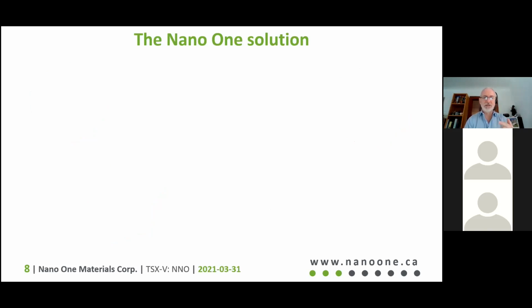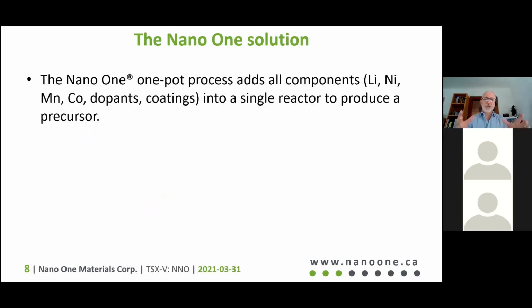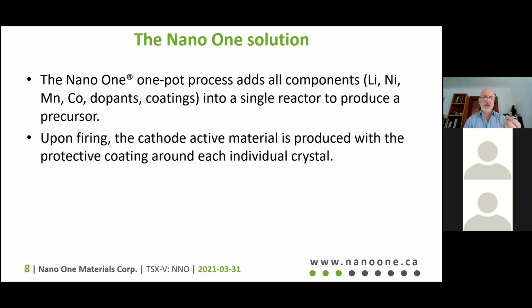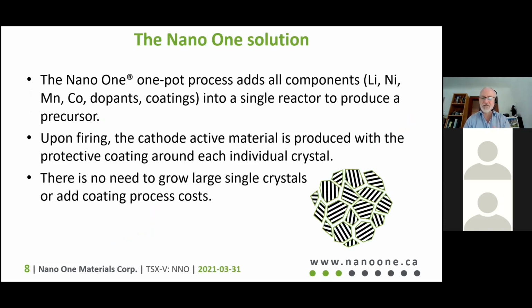The Nano One solution takes a slightly different approach. We have a one-pot process that puts everything into a reactor, including the lithium, the nickel, manganese, cobalt, dopings, and all the coating materials, all going into a single reactor. When you fire the material, you produce a cathode material in which every individual crystal, which is basically a single crystal but they're nanocrystals, has a protective coating. And this means that it doesn't matter when the crystal expands and contracts, because, as you can see in the schematic at the bottom right here, each individual crystal has a coating on it, so it doesn't matter if it fractures.